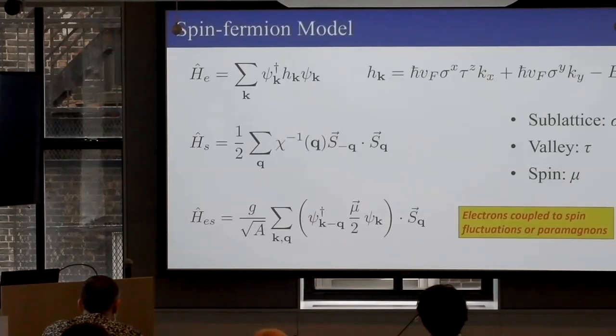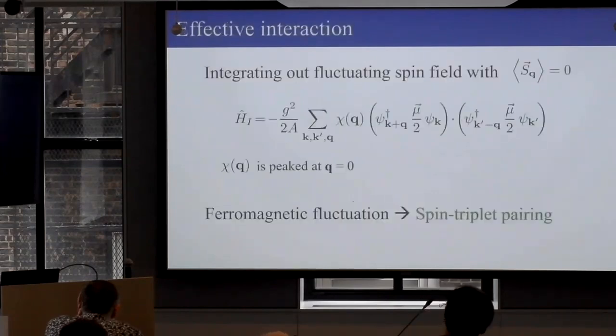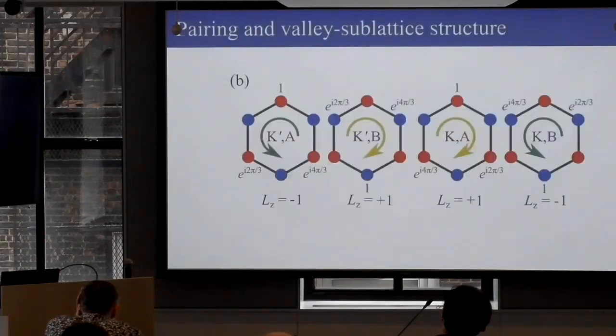And so here we invoke some spin fluctuations, which give rise to superconductivity, some kind of paramagnons. Since there is a ferromagnetic state nearby, it's not an absurd thing, but it's a phenomenological model. And then you do the same calculation that I was telling you about with the spin triplet, with this ferromagnetic fluctuation.